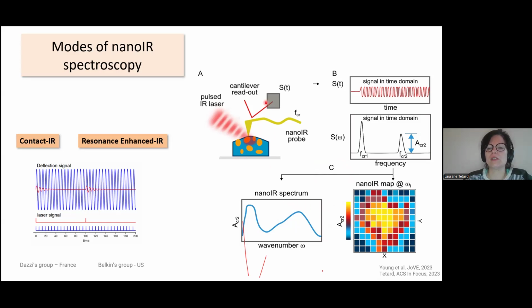And so now it's possible to shine the laser on the cantilever, do the process I just explained by looking at the Fourier transform and monitoring the amplitude. So in this case, for instance, the second peak as a function of wave number and reconstructing the spectrum. Or you can stay at a given wavelength, for instance, that excites CC bonds, and then you can move your tip across your sample and reconstruct a chemical map of your material.